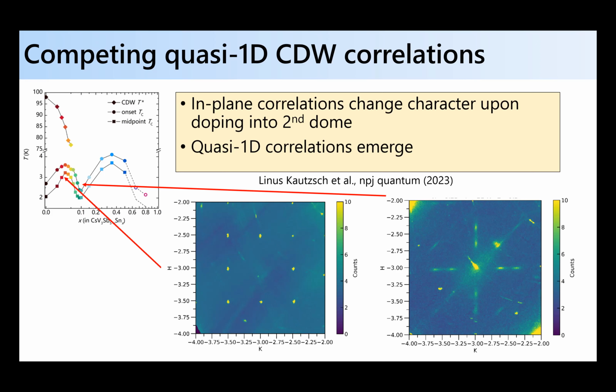But if you move to a point in which the CDW phase has nominally vanished, and ask what do the charge correlations do there? So here is what you see. These are qualitatively different than here. And if you fit this in a three-domain model, then effectively what you're looking at, again in the HK plane, is incommensurate quasi-one-dimensional charge correlations, okay? In three different domains of those, okay? So there seems to be a proximity of a quasi-one-dimensional charge instability.